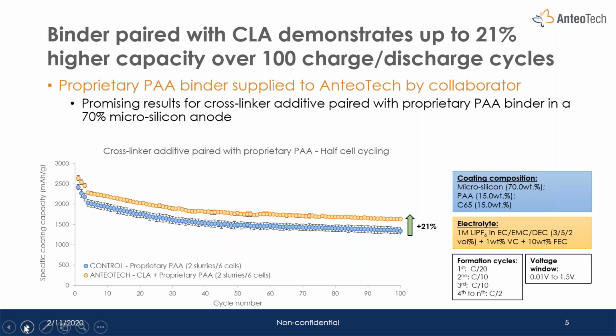Yes, so in this case, this was one of the first examples where a collaborator provided us with a sample of their existing advanced binder product, which in this case is a PAA or polyacrylic acid type derivative binder for use with silicon-containing anodes. And the objective of this evaluation was to pair this proprietary binder system, which is a commercial product, with our cross-linker additive and to evaluate the electrochemistry out of this binder cross-linker additive couple.